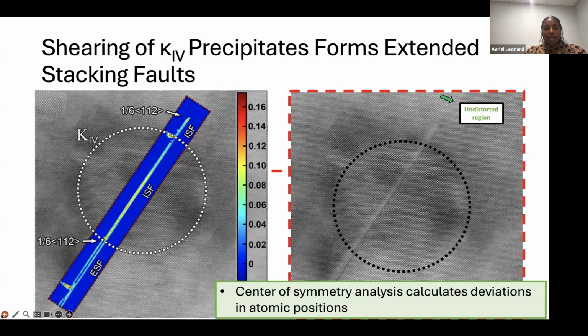We also learned that we have these extended stacking faults. So we can see here on the out of the shear precipitate that we have this extrinsic stacking fault. And we'll talk a little bit about what we think is happening to form extrinsic stacking faults in the material.